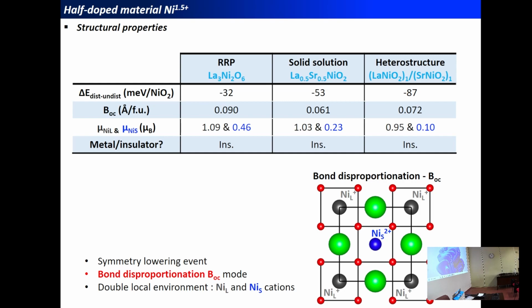And so we observe the magnetic moment associated with these 2 types of nickel cations. The nickel cation sitting in the large O4 group possesses a magnetic moment approaching 1 μB, whatever the type of structure we are studying, but the small nickel cation has a magnetic moment approaching 0 μB. And so this distortion, on top of the magnetic moment asymmetry, tells us that we can expect a charge ordering in the system associated with this type of breathing distortion.